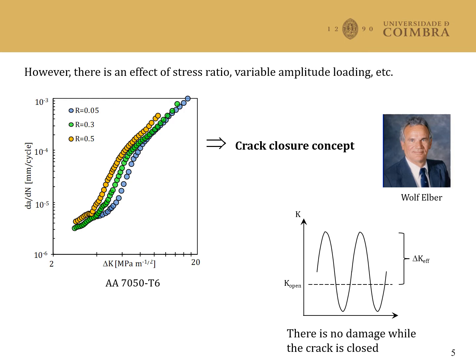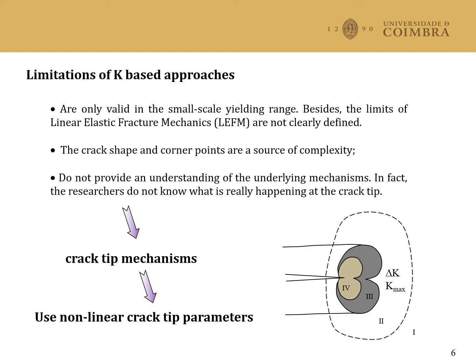However, the K-based approaches have several limitations. Namely, they are only valid in the small-scale yielding regime, which is not easy to define. The crack shape and the corner points are sources of complexity, and they do not provide an understanding of the underlying mechanism. In fact, researchers do not know what is really happening at the crack tip when using stress intensity factors. Therefore, it is recommended to look at crack tip mechanisms and to use non-linear crack tip parameters.